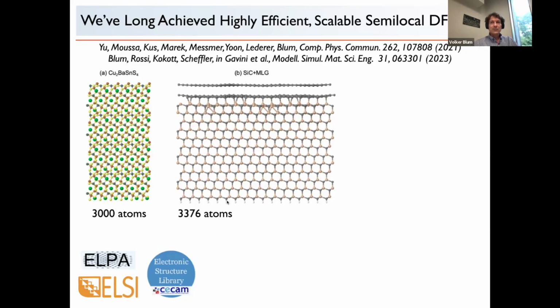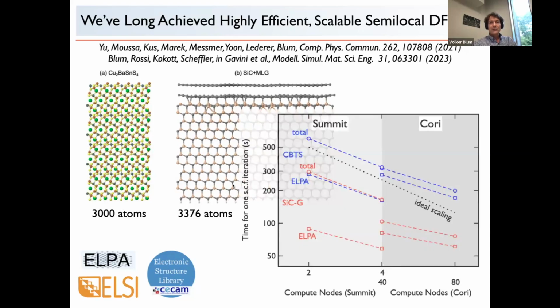This is a slightly different system, slightly different elements, but the key point is that we wanted to demonstrate that it scales. On a traditional CPU-based computer, the Cori supercomputer, which existed at NERSC, the National Energy Research Supercomputing Center, at the time, you see that the total time for this copper barium tin sulfide, the blue line here, scales pretty well, not quite ideal scaling, but this is from 40 to 80 nodes. So this is between about 1,000 and 2,000 processor cores. And the dashed line is marked ELPA.